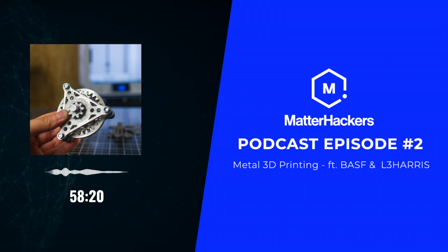But the main things to look for are really the basic guidelines that BASF gives, but they're more strict, I think, than most other rules with 3D printing. There's a bunch of different ways to handle thin walls with FDM printing, and you can print thin walls with this material, but you're not going to get successful debinding and sintering with thin walls beyond a certain point. So just because it prints doesn't mean that it'll be successful in the debinding and sintering process, and that's probably the most important thing to keep in mind.